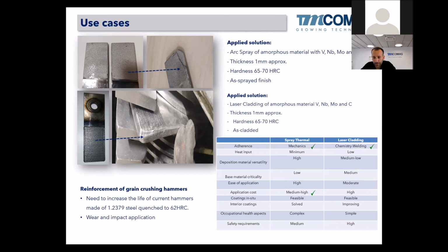So yeah, we did that, and after some hours we had the bad news that some of the coating had been damaged. So we have some spallation of the coating here in the point. So due to the impact, we thought that the impact was lower. We couldn't spray it by thermal spray. However,